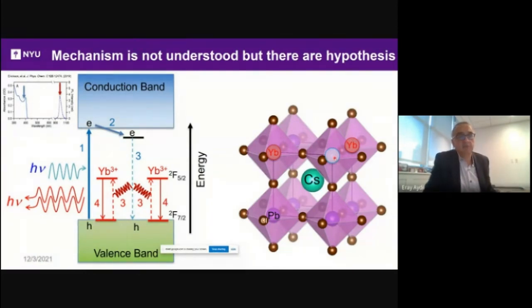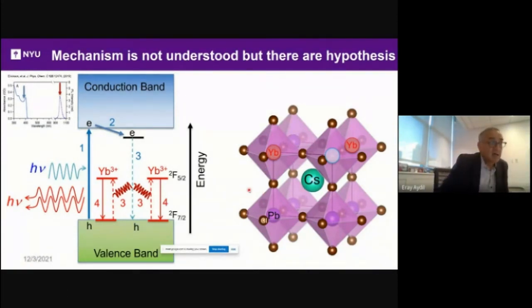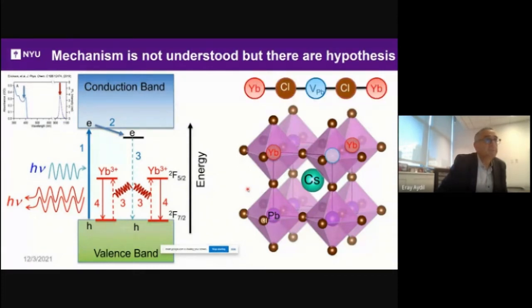The idea is that this vacancy traps the electron-hole pair, the exciton, and then because the ytterbium are in close proximity, energy from this defect can closely couple to the ytterbium. Whether this is true or not is an open question, but it is the leading hypothesis.